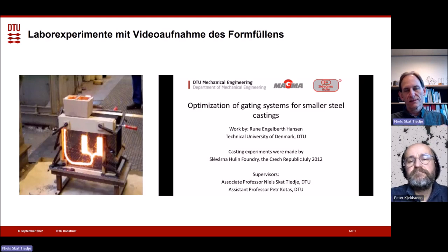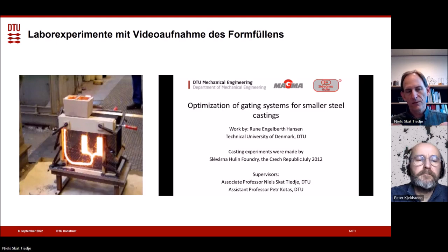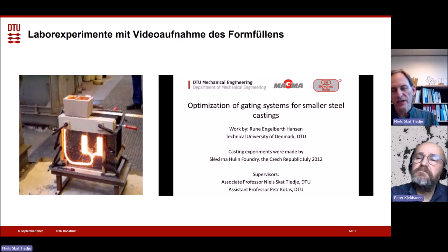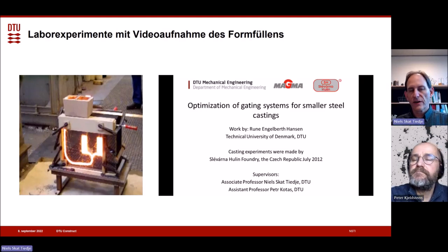Yeah. And that, because solidification in industrial processes is always a non-equilibrium process. On a good day, it's sort of a steady state, but everything is driven by heat extraction and kinetics of solidification. We have phase diagrams that guide us, but what happens in practice never follows the actual phase diagram. It's close, but always a little bit off. So to condition the melt, and nucleation and formation of graphite, for instance, in cast iron becomes really, really important.